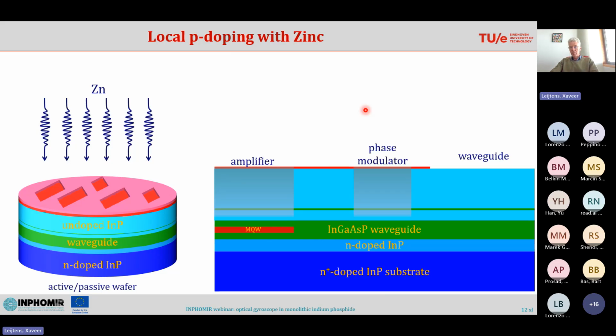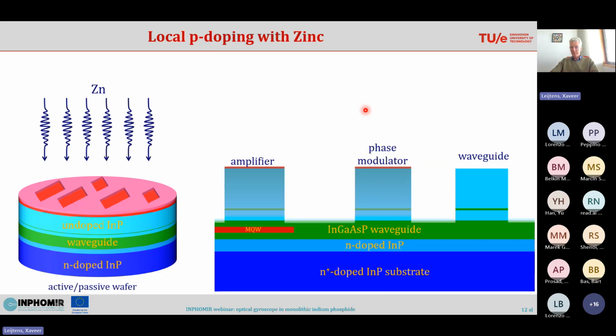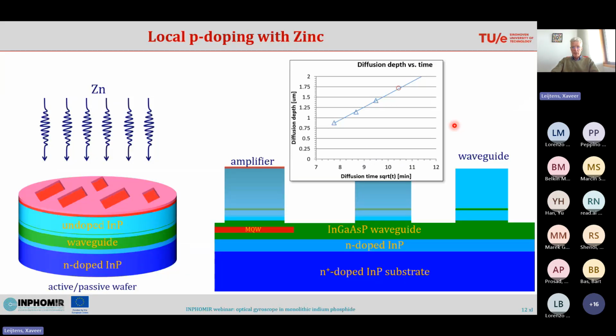Then we remove the mask again, and we etch the waveguides as we did before. And now we have a similar structure, but with doping only in the parts where we need it, and the waveguide is low loss without doping. This requires controlling the depth of the p-doping, which depends on the machine settings, but it's a process that is proportional to the square root of the time which you use to do this.